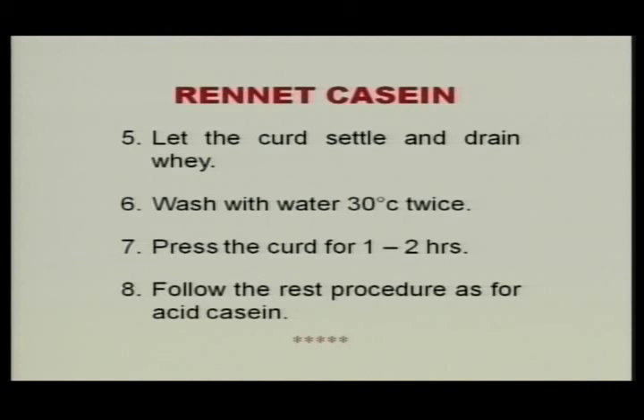After washing, press the curd for 1 to 2 hours. The rest of the manufacturing process remains the same as acid casein: spread the milled curd on tray dryers with inlet air at 70 to 75°C and outlet at 50°C, with slight agitation. The dried casein is then ground and packed in hessian bags or bags lined with polythene liner. Thank you.